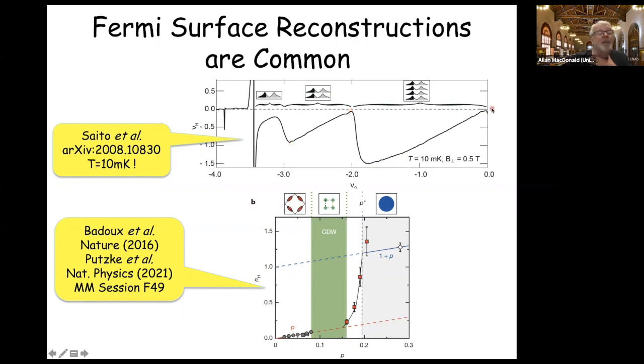And it's a measurement of the weak field Hall effect, which is a measurement of the area of the Fermi surface, and whether it's an electron-like Fermi surface or a hole-like Fermi surface. So this experiment says that I start from neutral graphene, start removing electrons. I have a hole-like Fermi surface that's getting bigger and bigger, and suddenly I have no carriers present. This actually occurs close to the insulating state at -2.